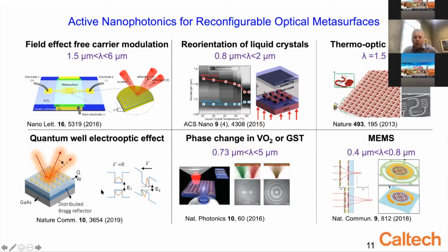I could make use of the electro-optic effect, which is applied across, for example, localized semiconductor quantum wells in III-V compound materials. This is the basis for the high-speed optical modulators that are used in modern communication systems. It's well known that they can operate in the tens of gigahertz range with fiber communication systems.